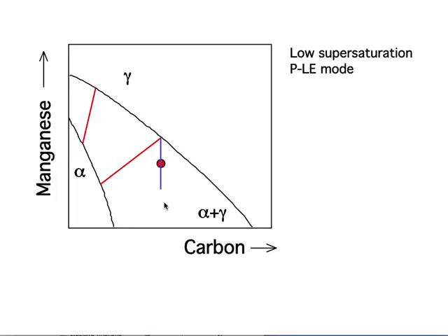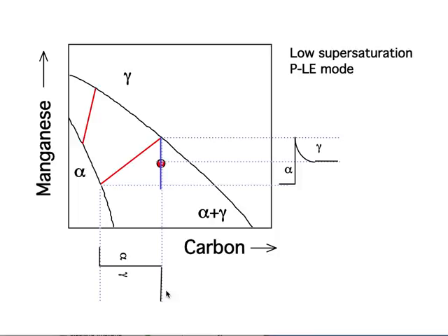All right. So the tie lines exist. They are easily calculated using thermodynamic methods. So we are not here looking at how to calculate a tie line, but any point on that phase boundary defines the tie line, which gives you the equilibrium composition of the ferrite. Okay. But you can see that the average carbon concentration in the alloy is equal to the equilibrium concentration in the austenite, so our concentration profile for carbon will be flat, and that will compensate for the large diffusion coefficient of carbon, and the manganese will be different in the ferrite and austenite, so there will be long-range diffusion of manganese. So by reducing the gradient of carbon, we compensate for its high diffusivity, and the tie line doesn't actually pass through C bar anymore. Okay? We maintain local equilibrium.